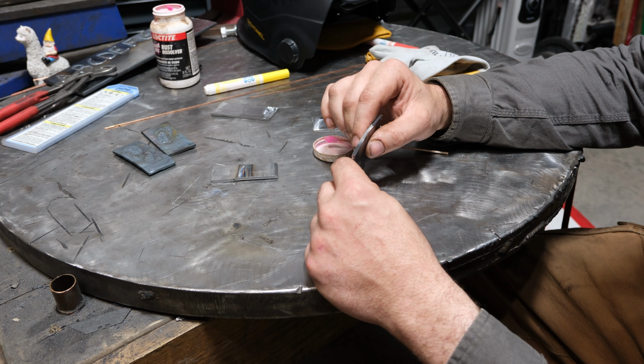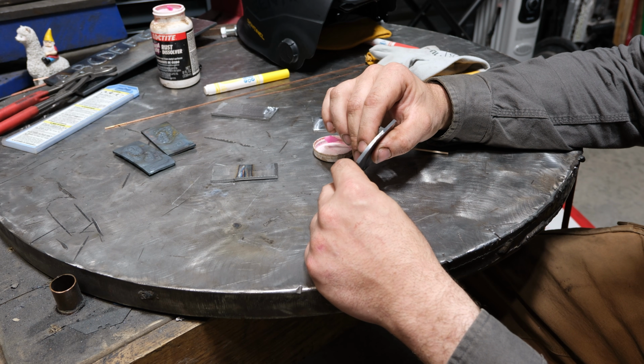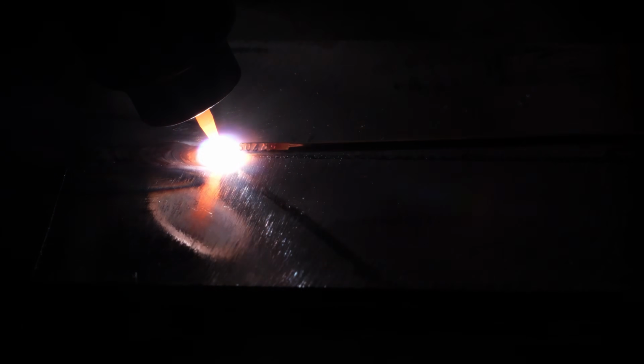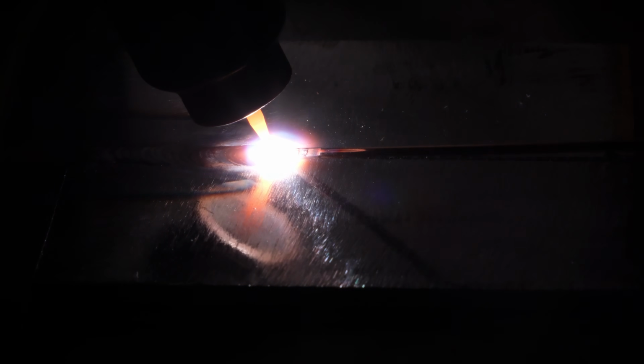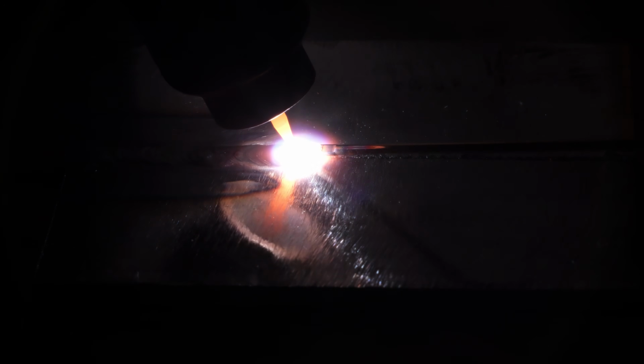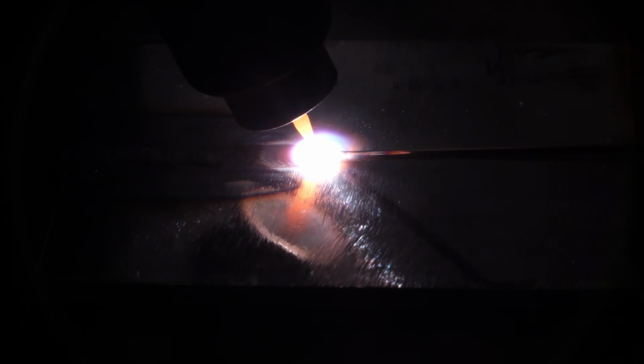Now we're going to do some arc footage where I add filler, and then we're going to cut and etch it and look at that and talk about that. So for this weld, I'm just starting the arc. I'm waiting for the puddle to get about 3 electrode widths, so 3 times as wide as a filler rod is. And then I'm just slowly pushing filler in. Now this, I'm more or less tapping the filler rod. I'm not pushing that much in. If there was a gap, or I was running more amperage, or the puddle was wider because I was moving slower, I would need to push in more rod.